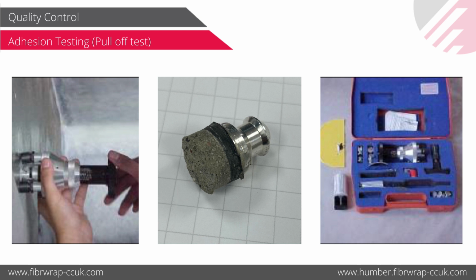So what we do is that we put a sacrificial patch on the same structure which we are strengthening. So that's what's shown on the left-hand side. Yes, in this particular instance, it was a beam flexural strengthening, but we put a patch on the side of it, so it can cure in the same environment. After the 100% curing, which as I said is 72 hours, we perform the pull-off test.